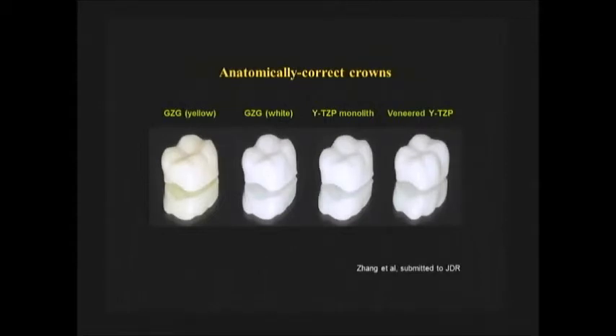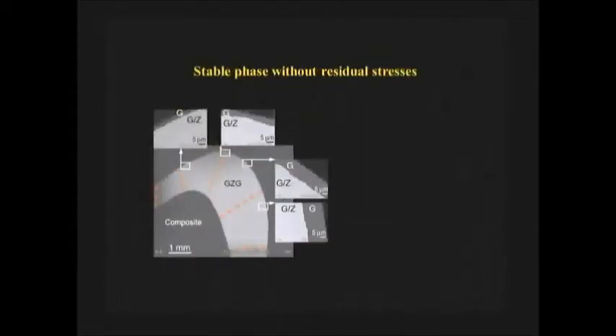across this way, and now you see the cusp. It's about 2 millimeters thick here, but the rest area can vary between 1.1 to 1.5 millimeters. So let's call the average about 1.5 millimeters. We infiltrate both top and bottom. When we section it, we see residual glass on the surface, followed by graded structures. The interior is zirconia. So what we do now is micro X-ray diffraction. The beam size is about 10 micron. We map from the surface in 50 micron steps going in to do two things.